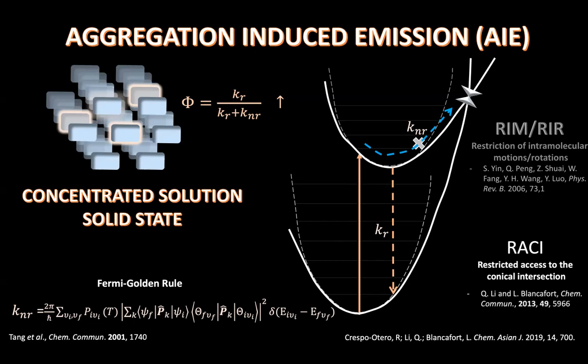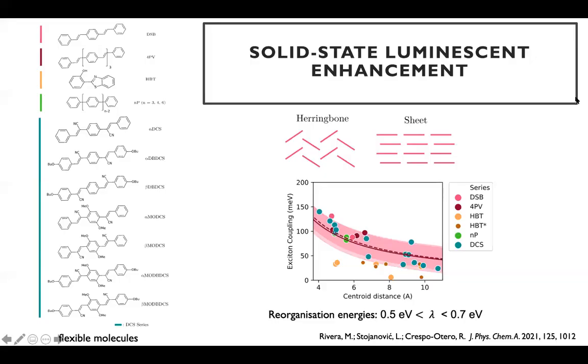We've been looking at a lot of systems showing this kind of behavior, trying to understand how you can maximize the emissive response in the excited state, and how you can avoid the decay through conical intersections. I'm going to show you a couple of cases related to that, and just want to illustrate some of the systems that we found. We have a collection here of flexible molecules. These molecules are quite flexible. However, when you put them in the solid, you will find that they emit light quite brightly. The reason for that is essentially that you have blocked the access to these conical intersections.